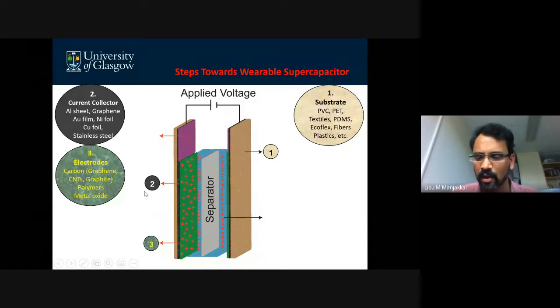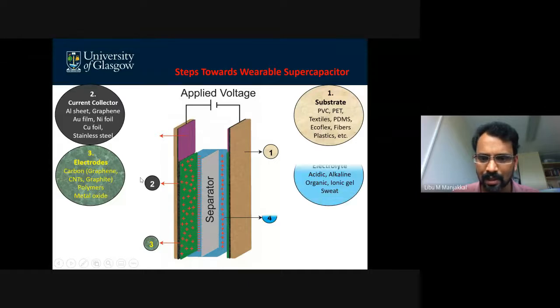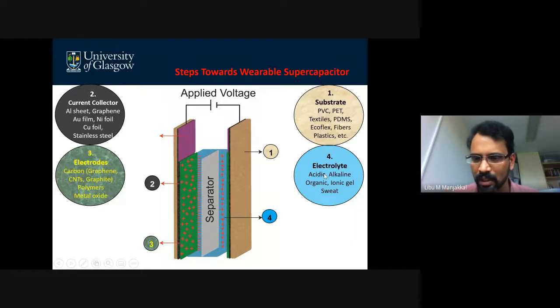Even your graphite pencil, your normal pencil, we can use as an active electrode because it's conductive, not fully conductive, but you can tune that into conductive. And then if you need to further improve your performance, you can use different types of metal oxide like manganese oxide, ruthenium oxide, or zinc oxide. There is much work going on in this area, or in conductive polymers. And then you need an electrolyte. You can use acidic electrolyte or alkaline electrolyte or organic, if you need to.